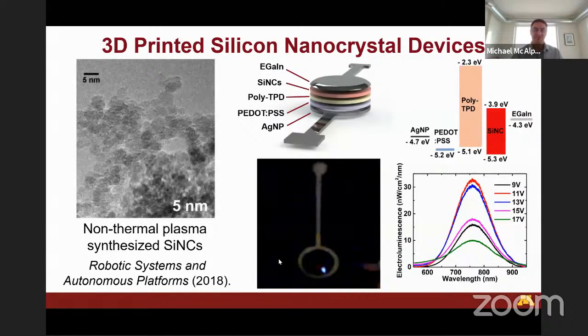So now we're actually taking silicon electronics and integrating it into the printing platform to create a device. And silicon, the band gap is in the infrared, but in the quantum dot, it shifts a little bit into the red. And so you can see in this movie, that's a red LED that's actually based on silicon nanocrystal light emission by incorporating these quantum dots into the structure. So basically taking silicon from the wafer, from the clean room, and incorporating this into the printer.